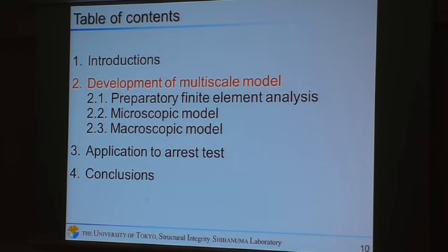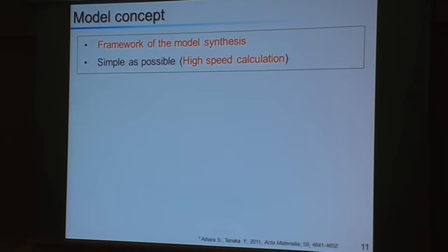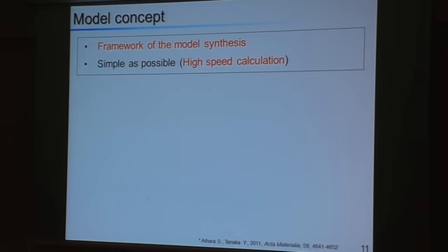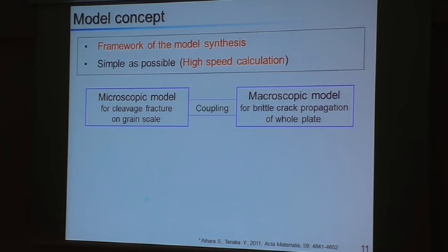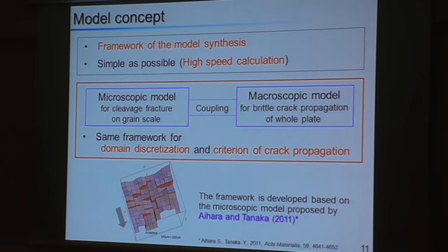Next, I'd like to talk about the multi-scale model. First, the model concept. The model concept is a framework of model synthesis, kept as simple as possible. Based on this concept, we developed the model as a coupling of a microscopic model for cleavage fracture at the grain scale, and a macroscopic model for brittle crack propagation of whole plates. The same framework for domain discretization and criterion of crack propagation is used in both models for simplification.